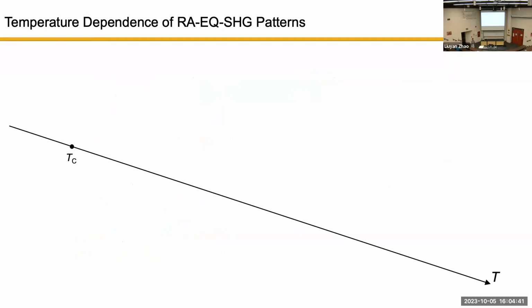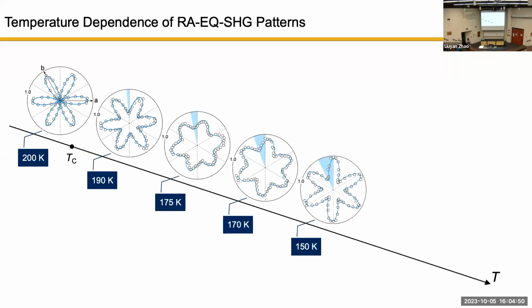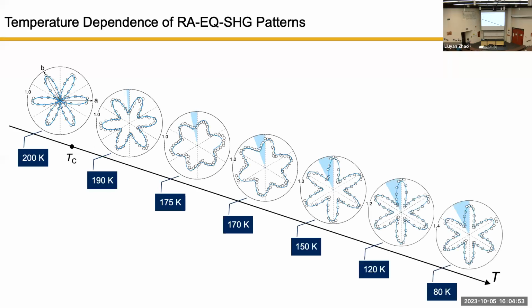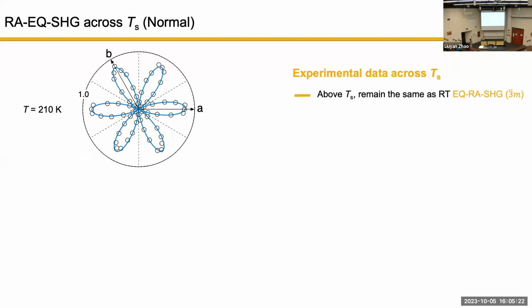Okay. So then now we have a way to really measure this centrosymmetric material. We want to see what happens if we cool down to low temperature across that critical temperature where the phase transition happens. So that is the result. It was initially this flower-looking thing that is very well aligned with the dashed line. The dashed line aligns to the valleys. As we cool down, below the critical temperature, a background all of a sudden pops up. In addition to that, you can see the flower patterns start to rotate away from the dashed line, which are the original mirror direction. So then if I still do a flip about the dashed line, my pattern cannot recover anymore. So this rotation suggests to us that we will have to break mirror symmetry to understand the data.